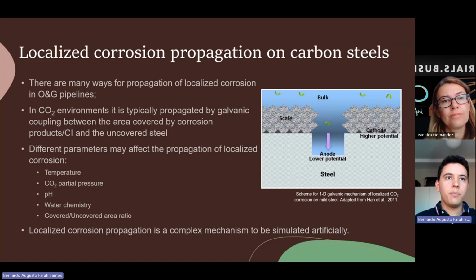Yeah, we had the problem, but how to get to it, because the propagation of localized corrosion is very hard to simulate artificially in the lab. So in the past, in the literature, there were several studies that used different electrodes. They were preparing one electrode to act as the cathode of this electrochemical cell, that would be the area covered with corrosion products or corrosion inhibitors, and the other electrode would be what they used to call the artificial pit, and promote this galvanic coupling using two different electrodes.